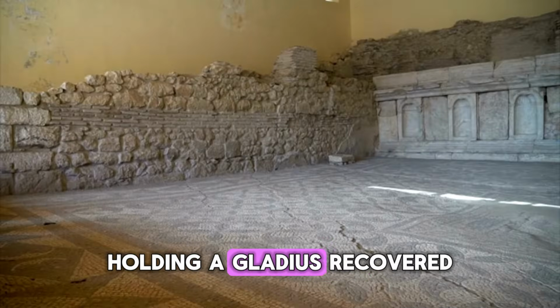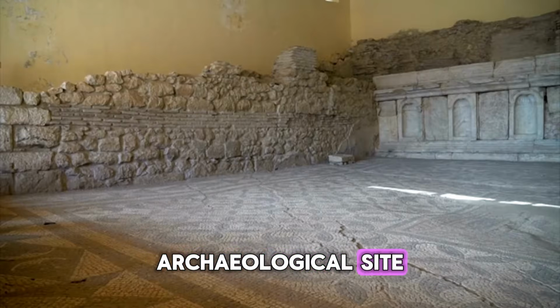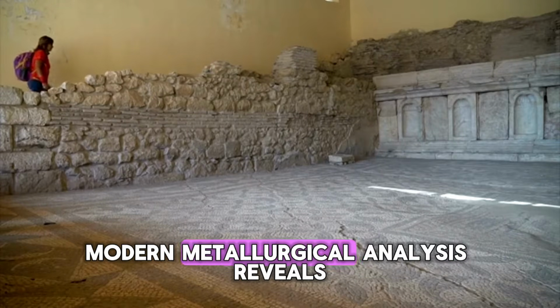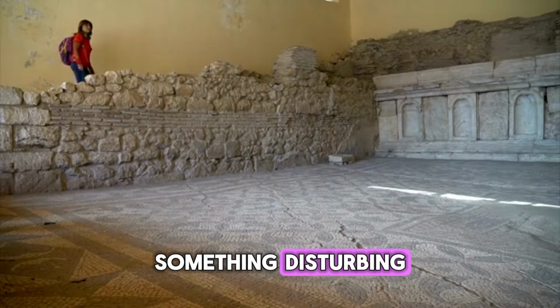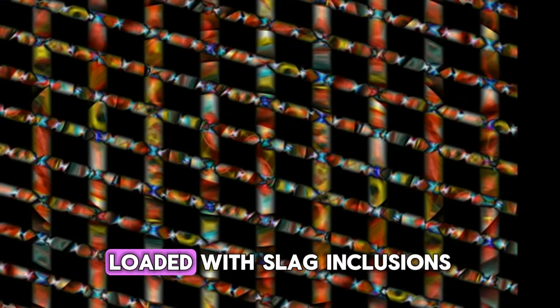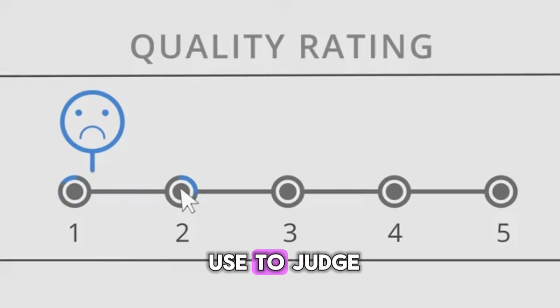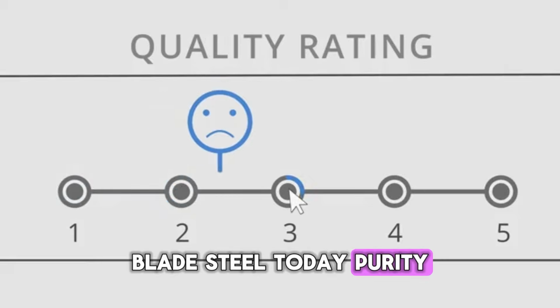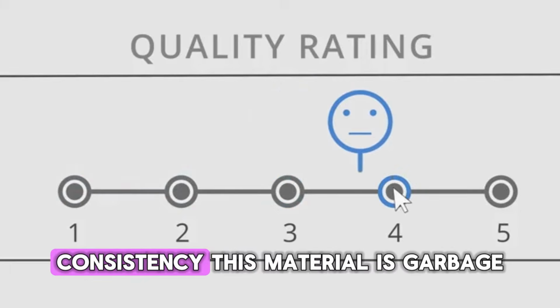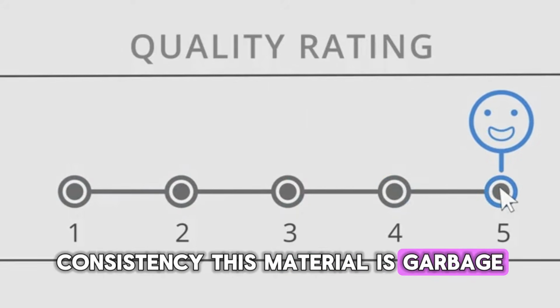Imagine you're holding a Gladius recovered from an archaeological site. Modern metallurgical analysis reveals something disturbing. The steel itself has a carbon content fluctuating wildly between 0.05% near the spine and 0.25% at the edge, loaded with slag inclusions that would horrify any contemporary metallurgist. By every standard we use to judge blade steel today, purity, homogeneity, consistency, this material is garbage.